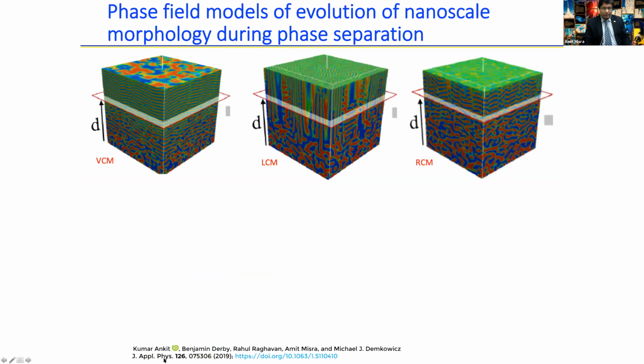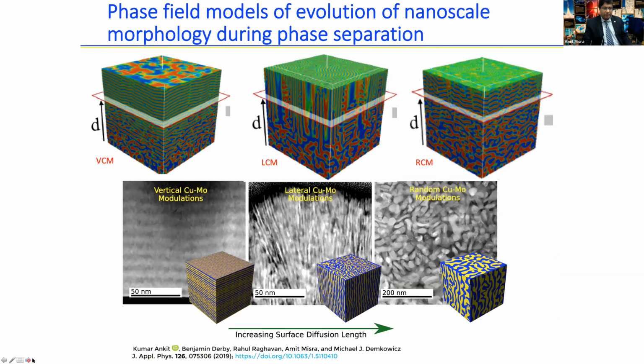So this is work by Kumar Ankit, and he could probably give a seminar on his work on this, phase field models of evolution of nanoscale morphologies during phase separation. The idea is that one can produce these different kinds of modulations. All of this is in the system copper and moly, by co-mixing at elevated temperature and sputtering, where we get instantaneous demixing. So you can have vertical striations, or you can have lateral, or you can have random.